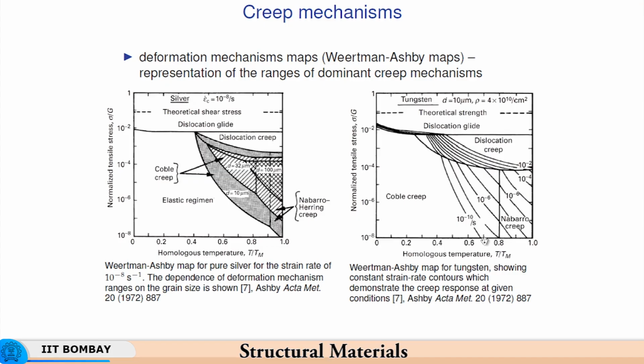So, you have in Coble creep at 0.6 homologous temperature for the same 10 microns grain size a much lower normalized tensile stress. So, the absolute value of the tensile stress may be higher than what you have in case of silver, but then the proportion is 10 to the power minus 7 or something like that. So, we should not compare these normalized figures at face value, because the absolute value here is going to be much higher as compared to that in case of silver.